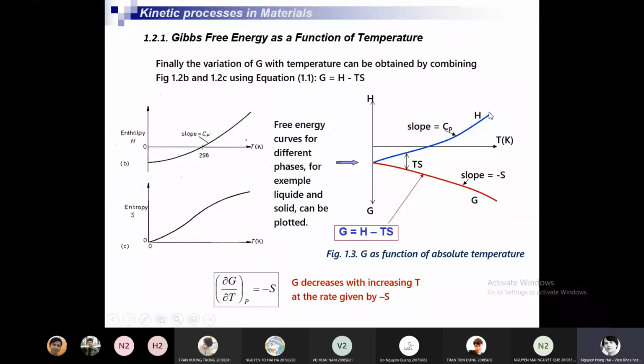The slope of the enthalpy curve is the specific heat, and the slope of the free energy curve is minus entropy. Minus because it decreases. The free energy decreases with temperature. Here the slope is positive because the enthalpy increases with temperature, but free energy decreases, so we have the slope minus here.